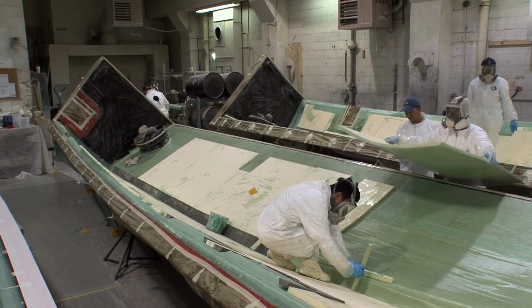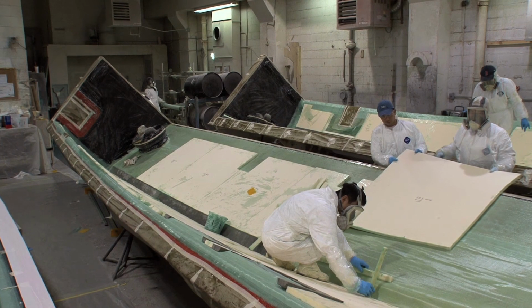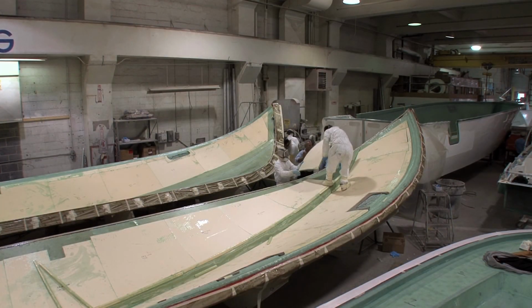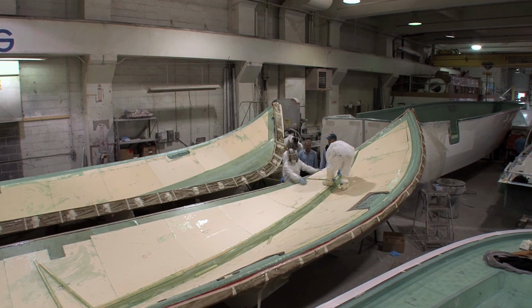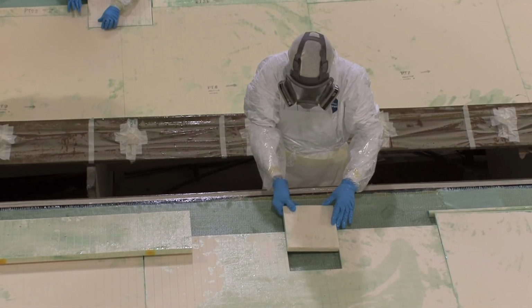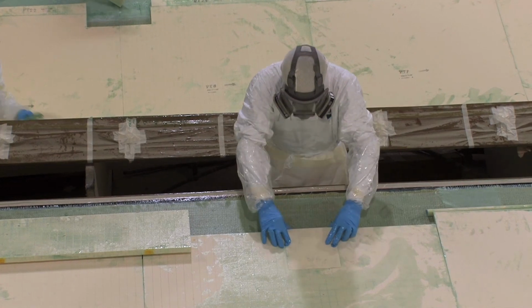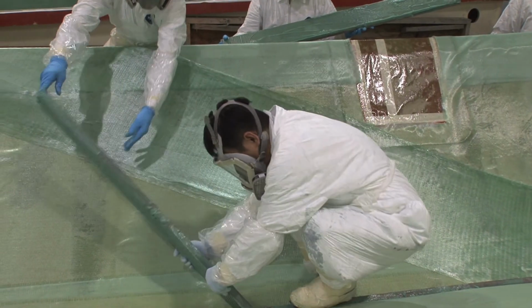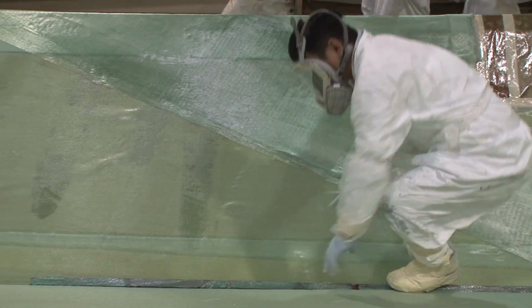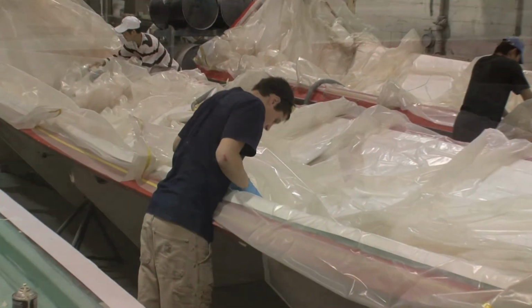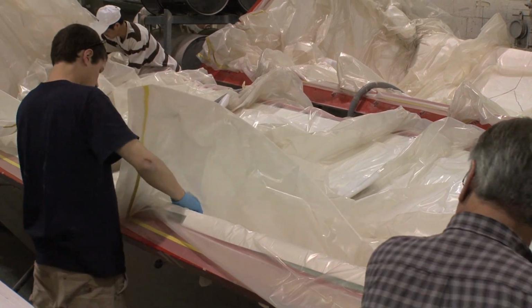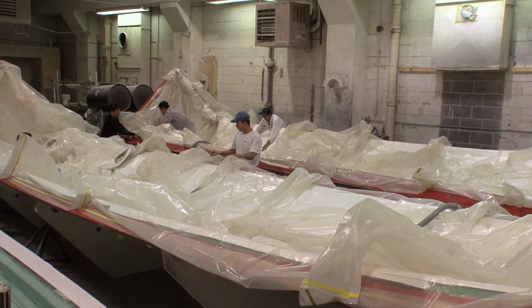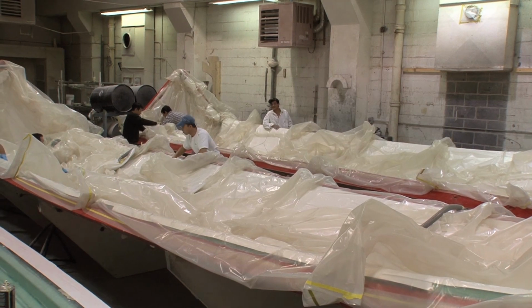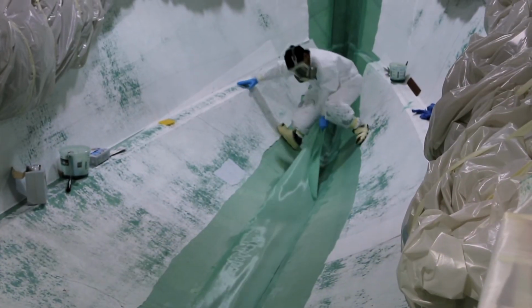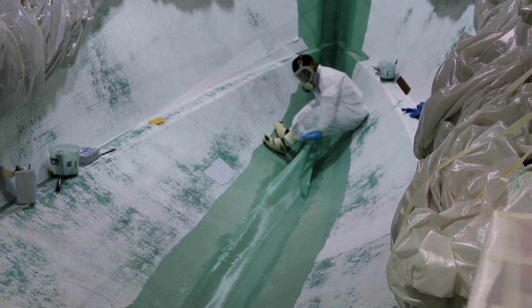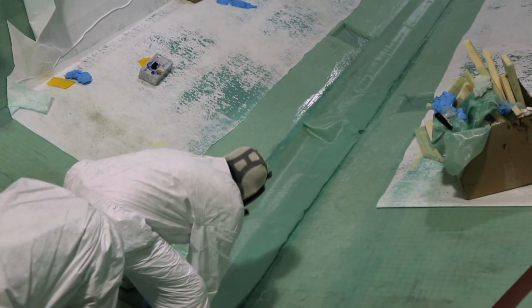Following the application of the outer structural laminates of fiberglass and Kevlar, we fit computer-cut panels of a waterproof structural foam core which has been engineered to take advantage of high-strength physical properties in the high-load areas and light weight in the low-load areas. Then we apply the inner plies of structural glass and encapsulate it in a vacuum bag. Under vacuum, the laminate is compressed at 2,000 pounds per square foot, compacting the glass for ultimate strength. The hull halves are joined and with 14 layers of triaxial glass create a solid glass centerline.